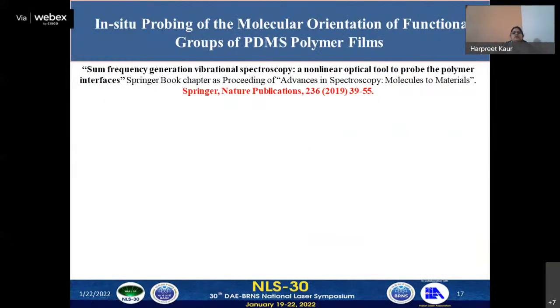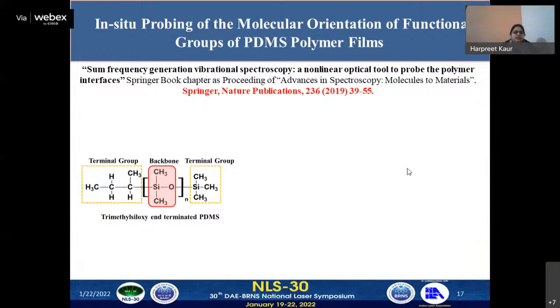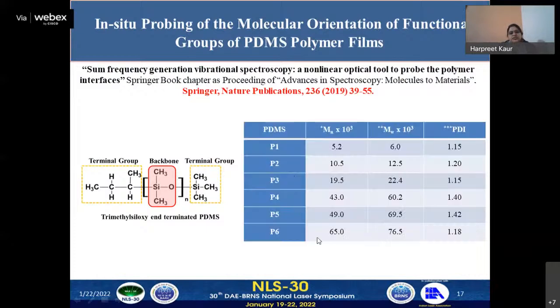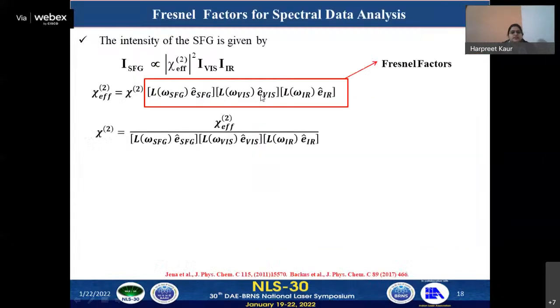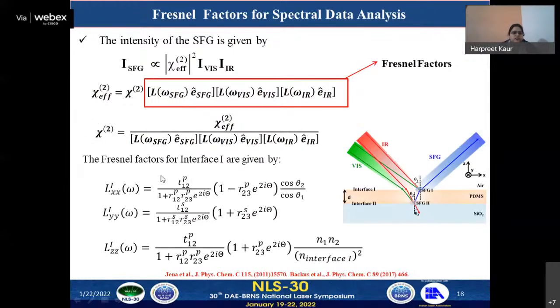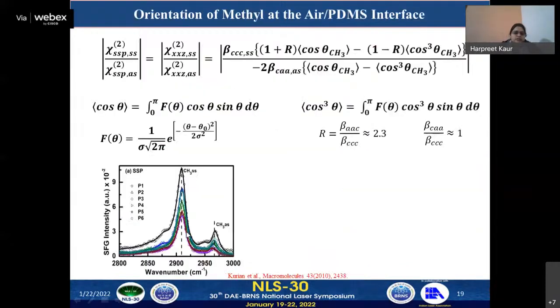Further, I will discuss the in situ probing of molecular orientation of the methyl functional group of polymer films with variation in molecular weight. So this is the molecular structure of PDMS, and we have found the impact of molecular weight variation on the orientation of the methyl group. For this, first we have done theoretical calculations of the L factor corrections to get the real response of the medium. And these are the expressions for the Fresnel factor at interface 1, which we have applied to the experimentally determined SFG spectra.